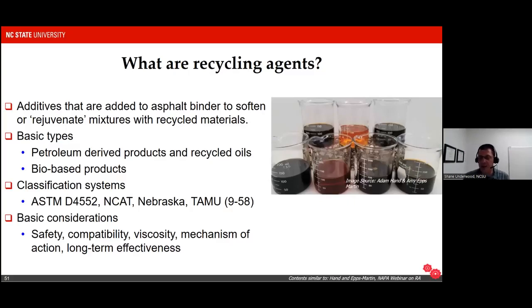What most agencies seem to be doing is adding the recycling agents in a way to rejuvenate the high temperature grade, so that they get as much rejuvenating agent in that mixture as possible and still have a material that's unlikely to rut. So usually you're going to add as much recycling agent as you can so as not to decrease the high temperature grade below 64. And that's as high as you go. And that changes all of the rheology. But yeah, the focus has been on durability and cracking. And so most people are trying to put as much in there as possible to avoid that cracking problem.